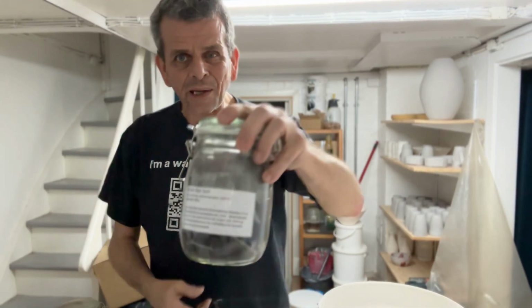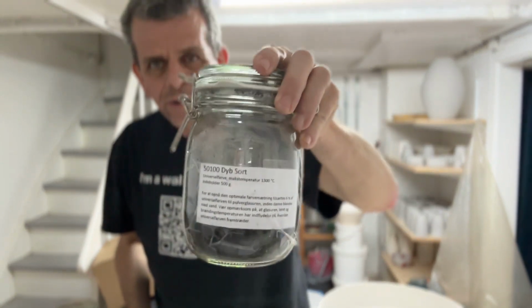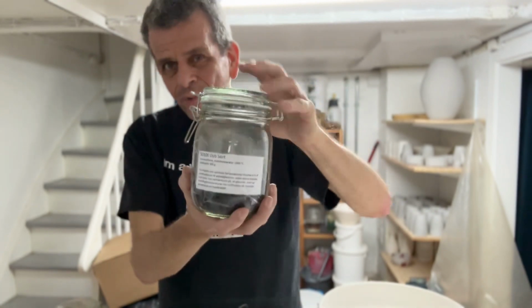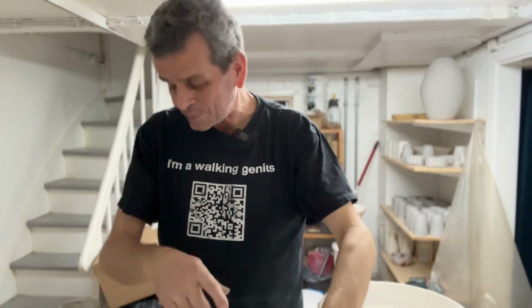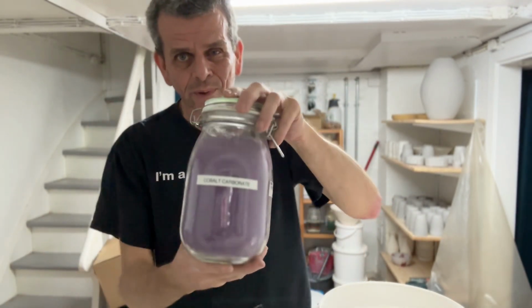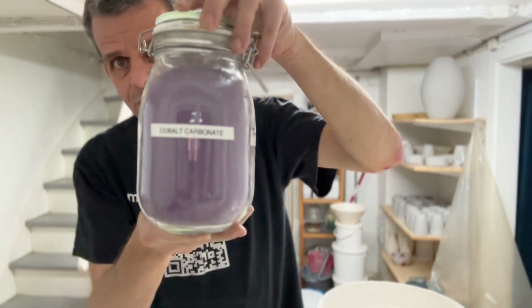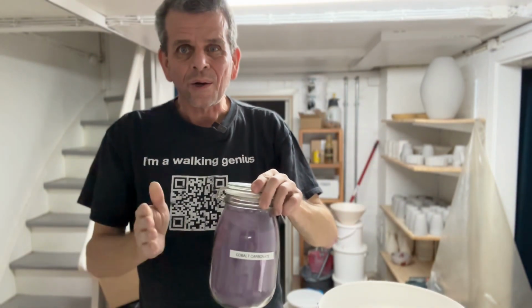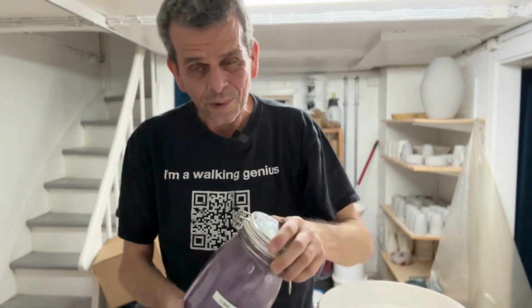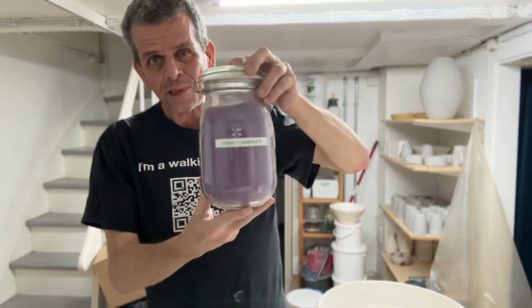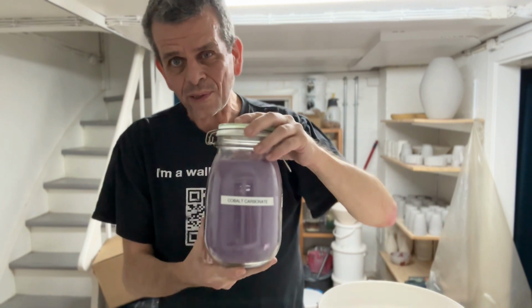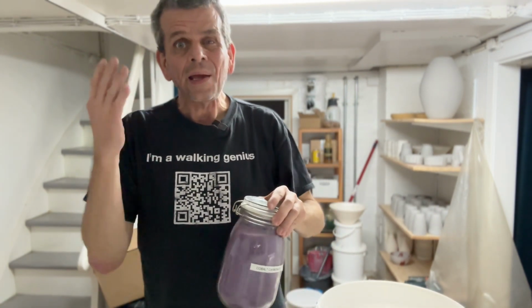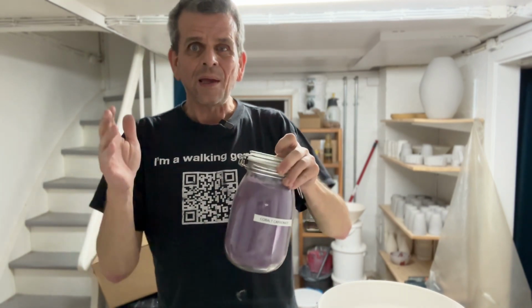The last 2 components is the black stain. And again, this is from a local supplier, a deep black. Black is rather expensive, but not as expensive as the cobalt carbonate. Anything with cobalt is just super expensive. Cobalt carbonate, cobalt stains, cobalt oxides. This is 1 kilo, and it's about 1,000 Danish kroner. So what is it? 150 US dollars, something like that.